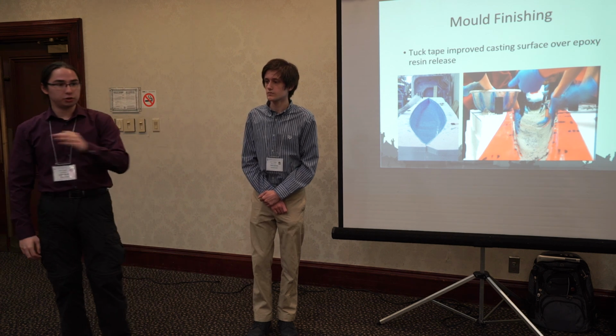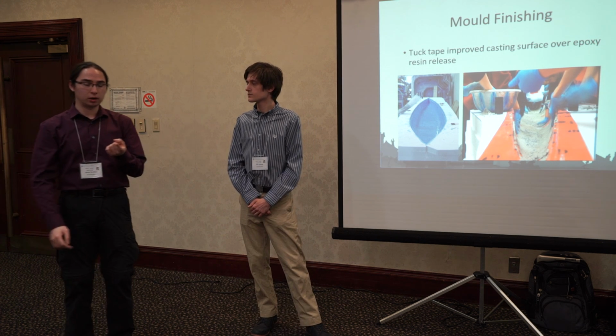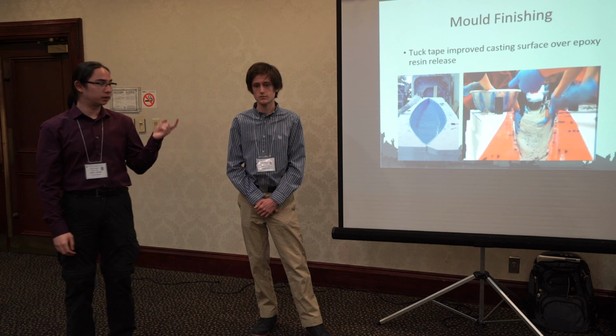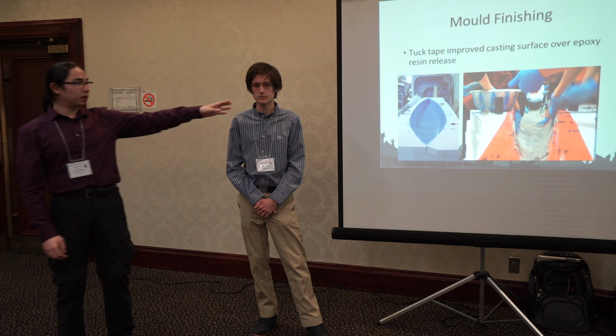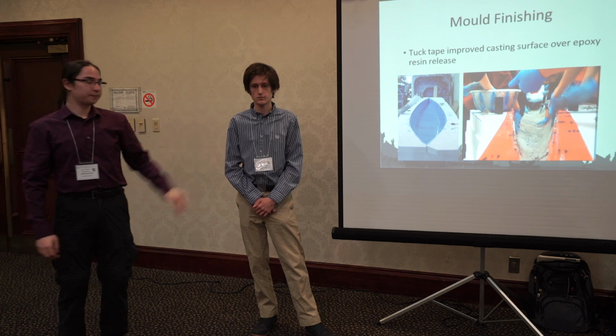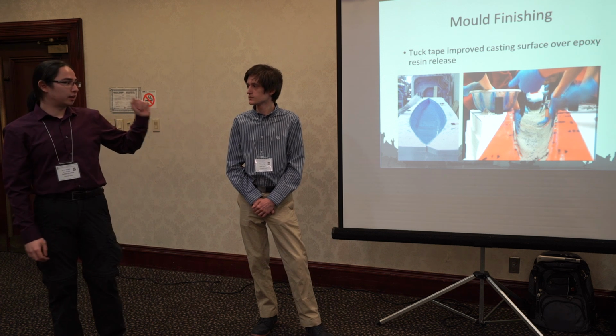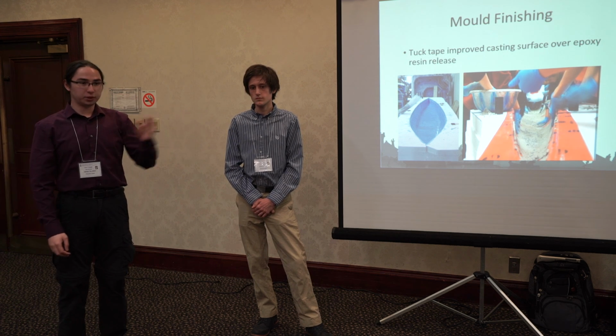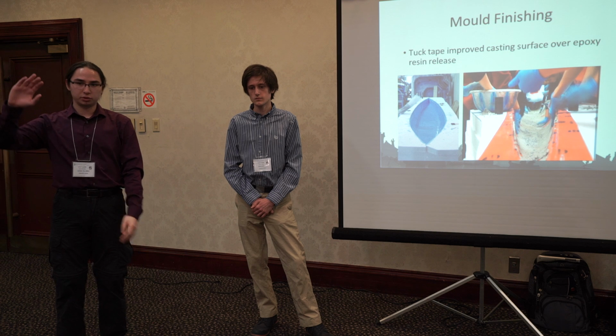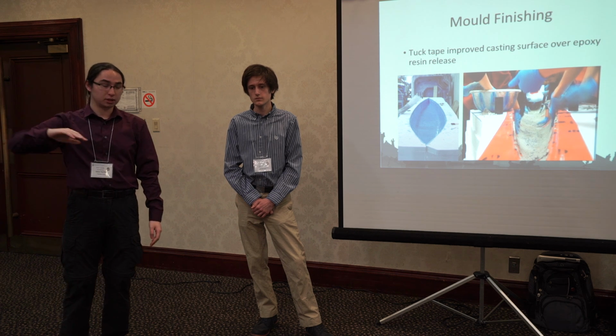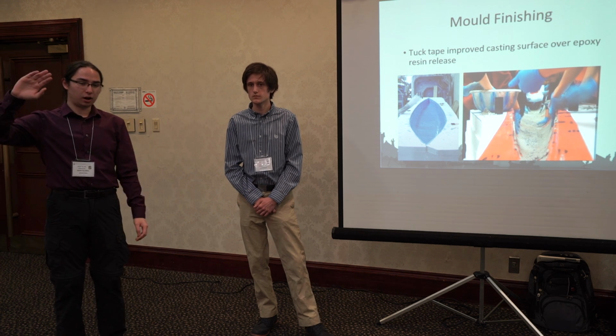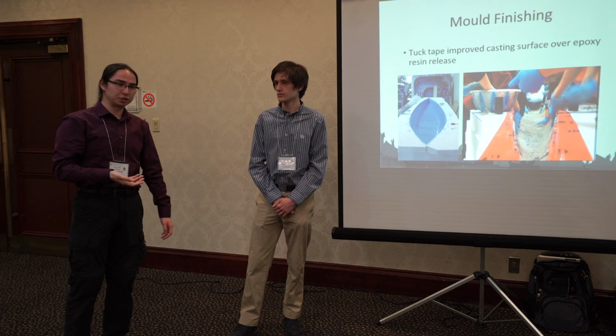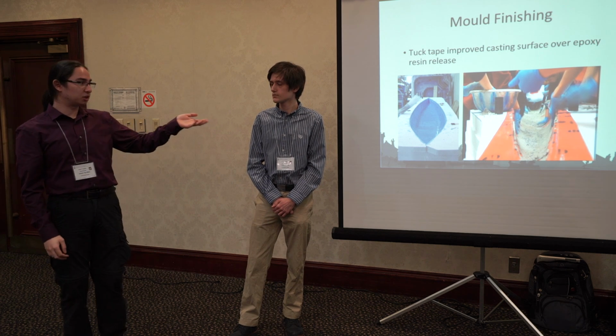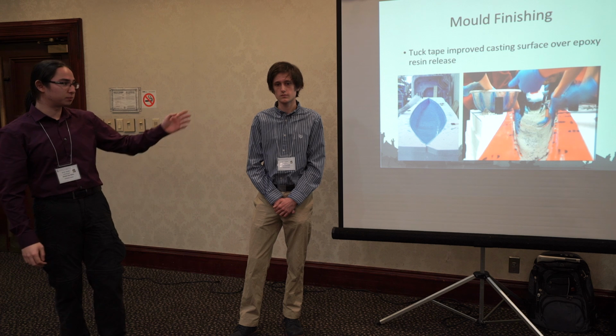The problem with using shrink wrap is that it's both easy to tear while casting upon it, and it doesn't release nicely. So we switched to an epoxy resin release. That was last year, and what we found out is that even with the epoxy resin release, even though it's supposed to be a release agent, we'd have to coat it with another release agent just to get the canoe out of the mold without having to rip apart the mold.